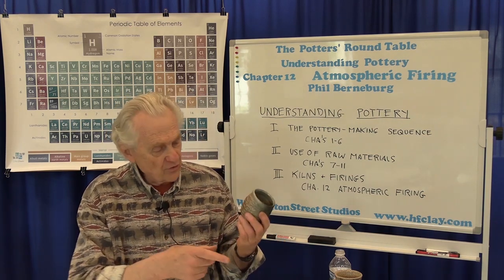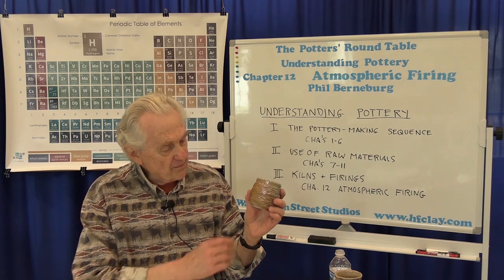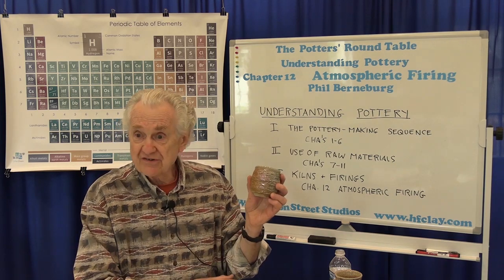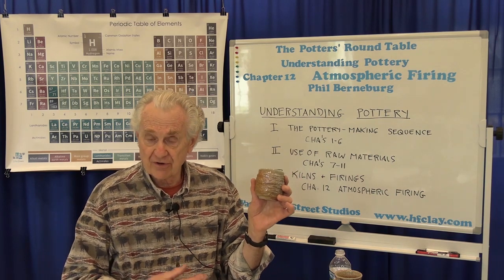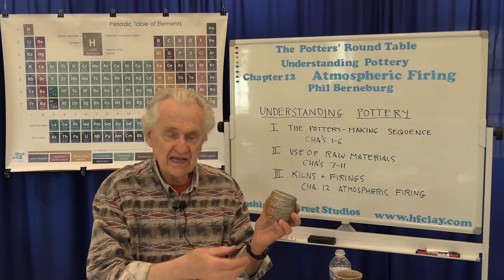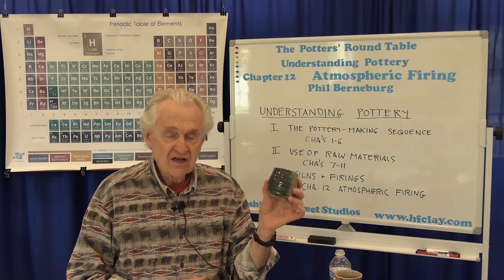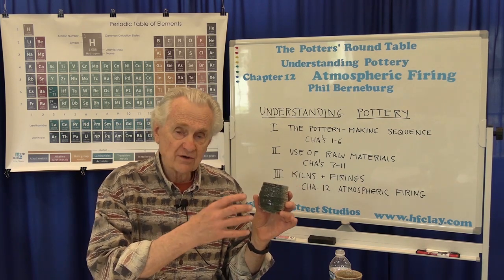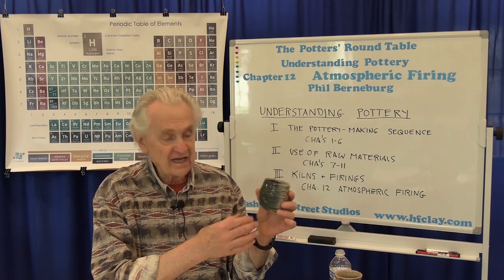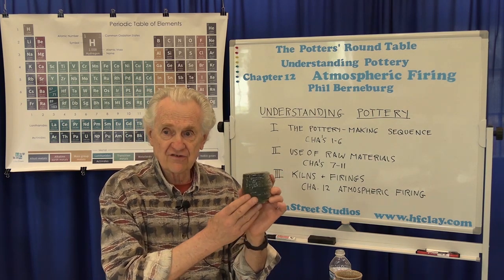Here's an example — a little cup that sort of embodies all the different things you can get from soda firing. The backside of the cup is just a light gray stoneware — there's no glaze below the rim. All this coloration is basically the flashing produced by contact with the soda vapor and also the wood. If you get a lot of sodium deposited and it continues to react with the clay, it can actually produce a fairly thick layer of glaze on the pot. It's black because this happened fairly early in the firing, so we also got carbon trapping. While the sodium was reacting with the clay and producing a glaze, especially in a wood firing, a lot of soot is commonly produced — the carbon was actually trapped in the glaze. So the thick layer of black glaze was not added; it was formed by the contact of the sodium vapor with the clay.